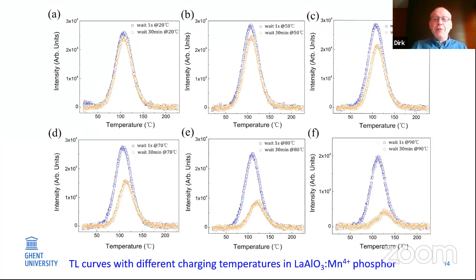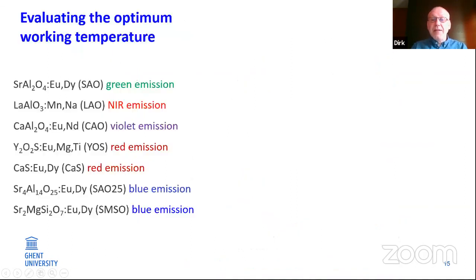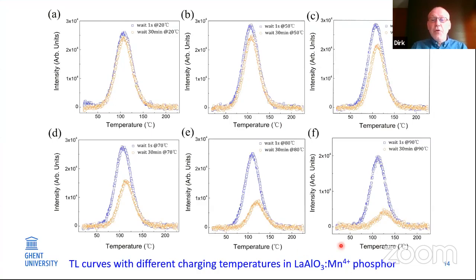We also did this for different materials. This is the same kind of measurements for lanthanum aluminate with manganese 4+. This is an infrared emitter. And here we see if we do the experiment at 20 degrees centigrade, we hardly see any difference between these two curves, which means that there's hardly any thermoluminescence at 20 degrees. It's better at 50 degrees, larger difference, 60 degrees, 70 degrees, 80 degrees. So here we really need a higher temperature to achieve persistent luminescence.